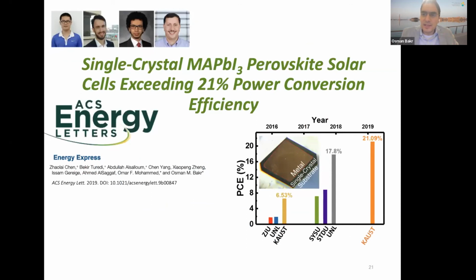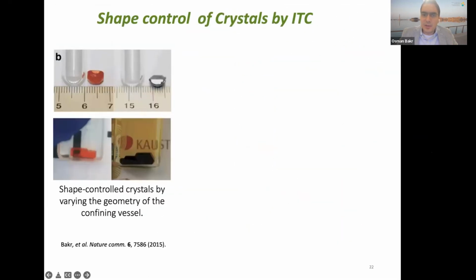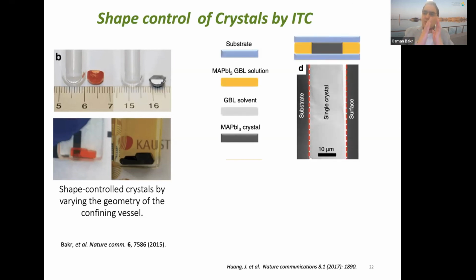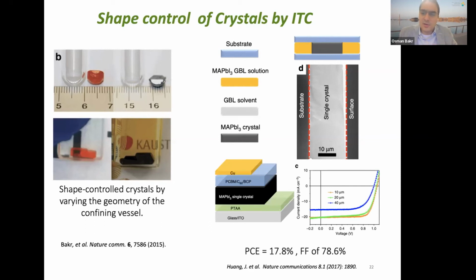Then we started looking at how can we advance this field even further. And by chance, one of the really good researchers in the community, Professor Jinsong Huang, found that you can adapt the method we developed for shape-controlled crystal growth, and you can apply it instead to growing crystals between two substrates. And if one of your two substrates is your hole transport material, then you could peel that off and you could evaporate your electron transport layer and you could form your crystal. And that was an interesting discovery, and actually led to a relatively good solar cell.